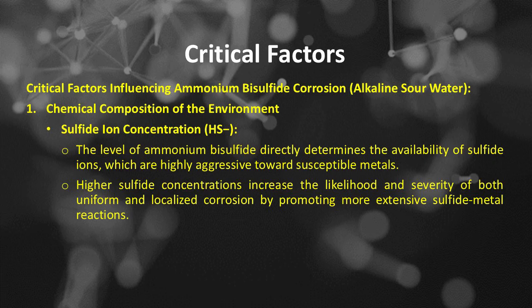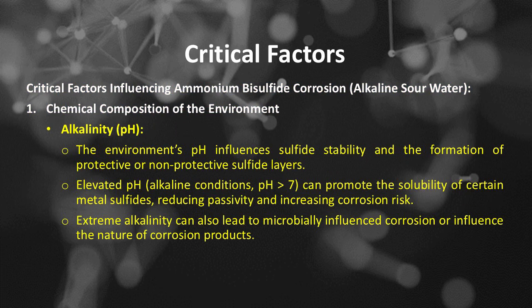Higher sulfide concentrations increase the likelihood and severity of both uniform and localized corrosion by promoting more extensive sulfide-metal reactions. The second is alkalinity or pH. The environment's pH influences sulfide stability and the formation of protective or non-protective sulfide layers. Elevated pH, alkaline conditions, pH greater than 7, can promote the solubility of certain metal sulfides, reducing passivity and increasing corrosion risk. Extreme alkalinity can also lead to microbially influenced corrosion or influence the nature of corrosion products.